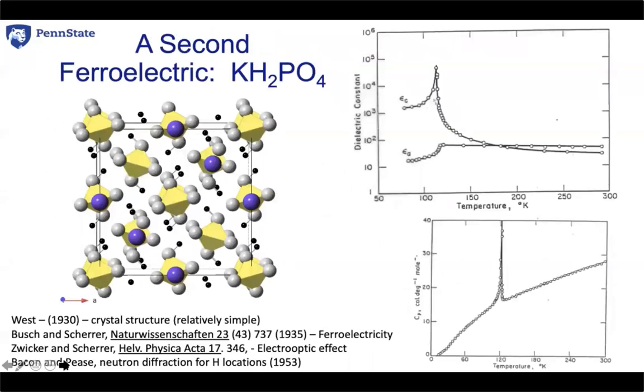It wasn't until 1935, so 15 years later, that a second material was determined to be ferroelectric. Thankfully, the crystal structure of this was known from West's work. I illustrate it here. It's an orthophosphate in which the hydrogen bonding can change its position. And based on that, there are small rearrangements of the crystal structure of the material that ultimately produces the ferroelectric phenomena. So Busch and Scherrer were the ones who demonstrated that this material is indeed ferroelectric.